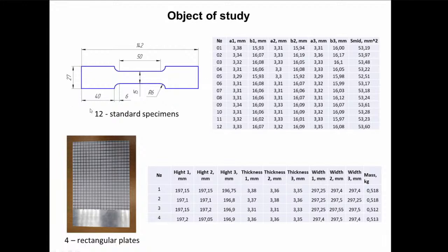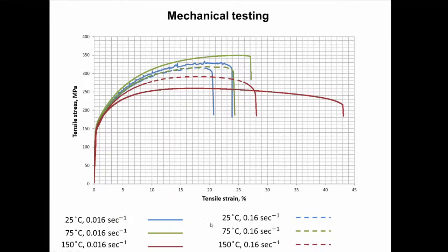We used 12 standard specimens for this, and here are the geometrical and mass characteristics. Also we took 4 rectangular plates as targets to test during high-speed collision, and we were trying to obtain the ballistic limit for this material also. As you can see, we made 6 groups of experiments for different loading speeds, which were near quasi-static loading with slight differences, and for 3 different temperatures: the ambient temperature of 25 Celsius, 75, and 150 Celsius.